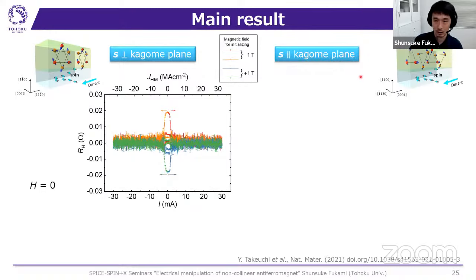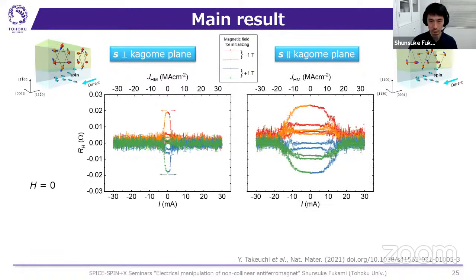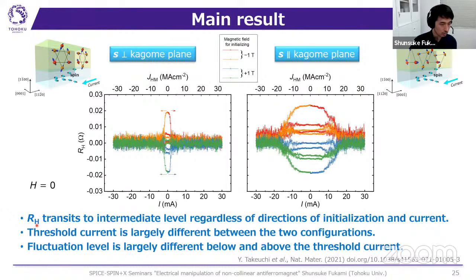So next, in the next configuration, the result is as shown here. In this case, the results are qualitatively the same, but the threshold current to change the state is different by about a factor of 10. So the points are that the Hall resistance transits to an intermediate level regardless of the directions of initialization and current. And the threshold current is largely different between the two configurations. And also the fluctuation level of the Hall resistance is largely different below and above the threshold current.